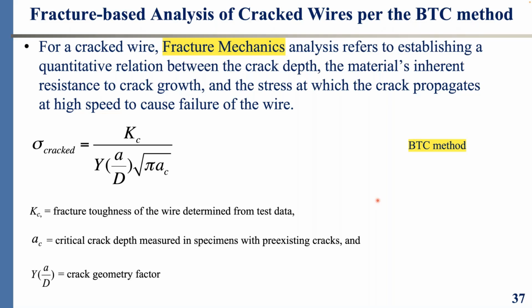Fracture-based analysis of cracked wires that is used in the BTC method. Of course, when we have a cracked component, any structural steel component that has a crack, all the elastic analysis that we so carefully do with finite element and this and that is invalid, is insufficient. What takes over is the fracture parameters, and in terms of that, the K sub C, which is the fracture toughness of the bridge wire, that was an unknown quantity before our work.